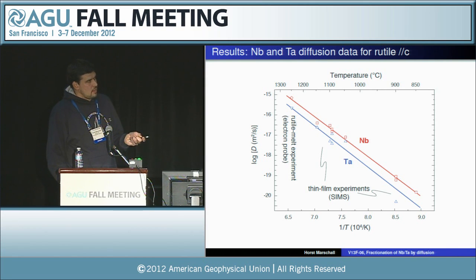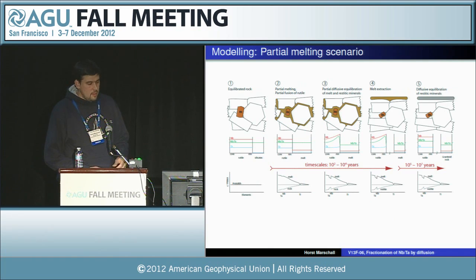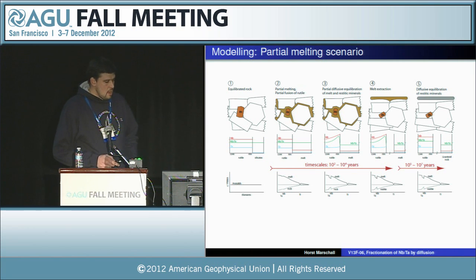And in every single case, it's important that we determine the two elements at the same time, simultaneously. So although there's a certain scattering, every individual experiment has a very solid determination for the relative diffusivity of the two elements. So in summary, niobium is 4 times faster than tantalum. And then we take that information and look at partial melting.